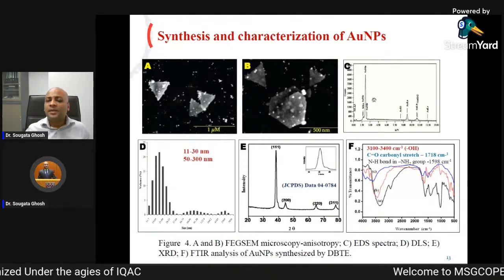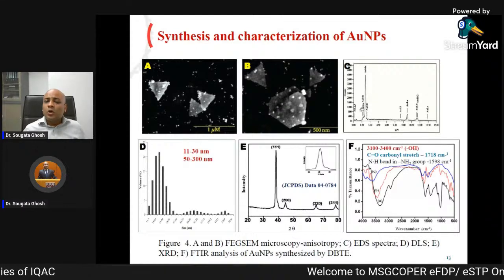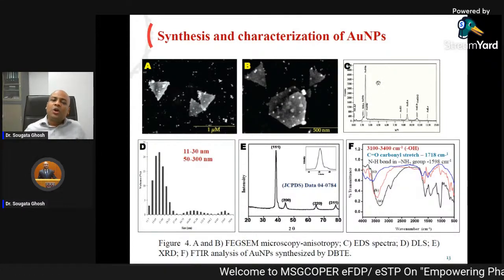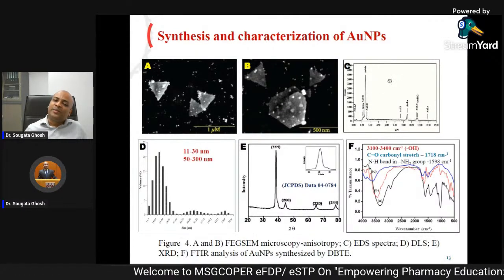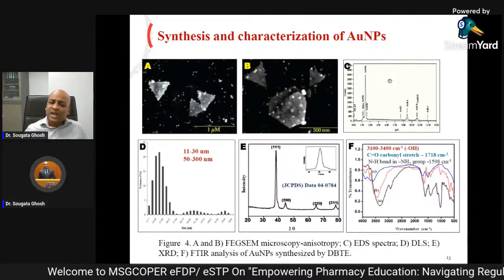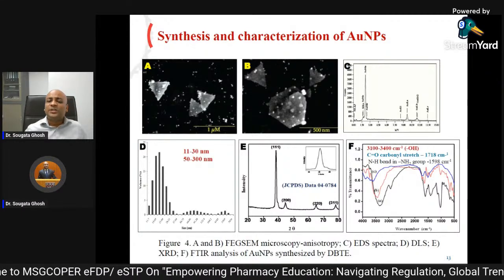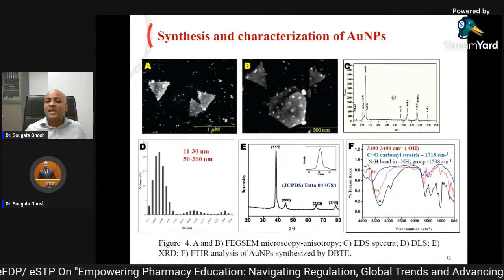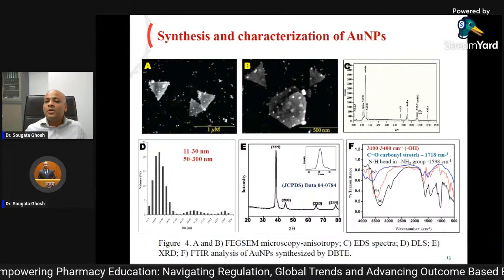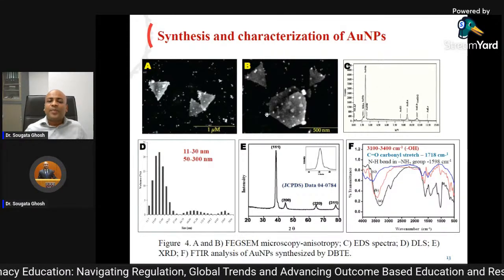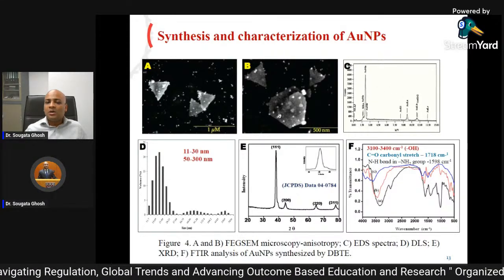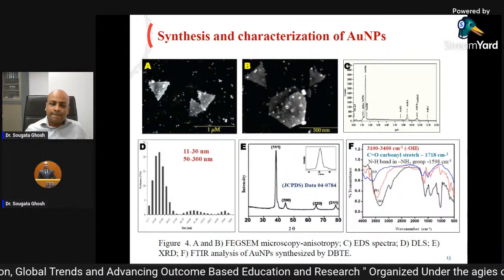Next, we wanted to see whether it is really gold or not. So there is a method called EDS, energy dispersive spectra, that will tell you which element is present. So we got the peaks of Au. You can see Au. So that means these particles were nothing but gold. So they were gold nanoparticles.